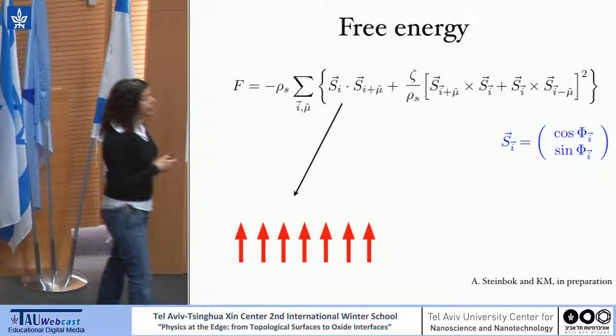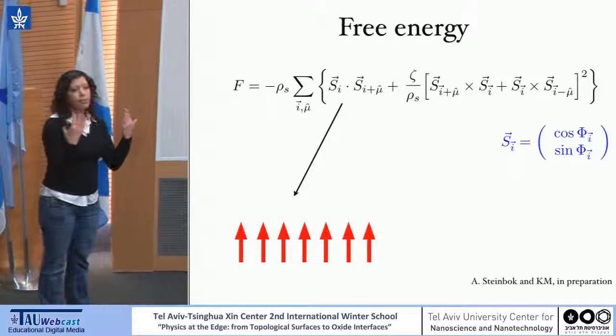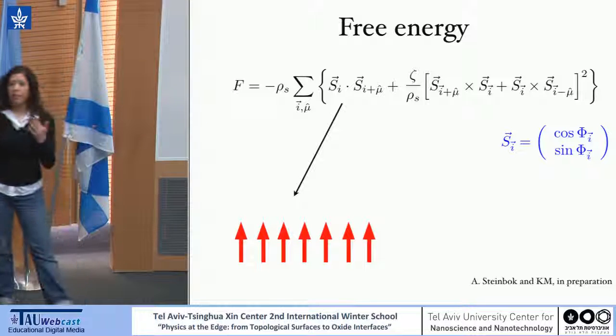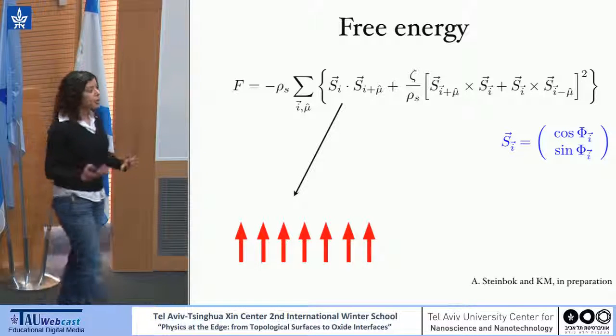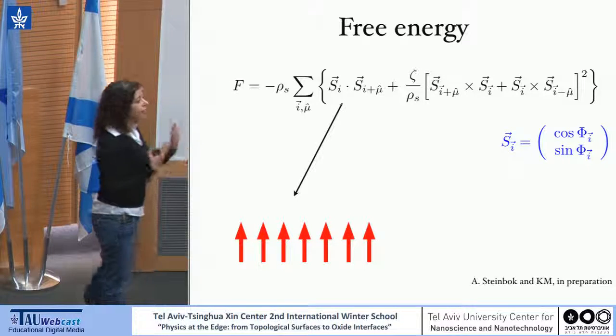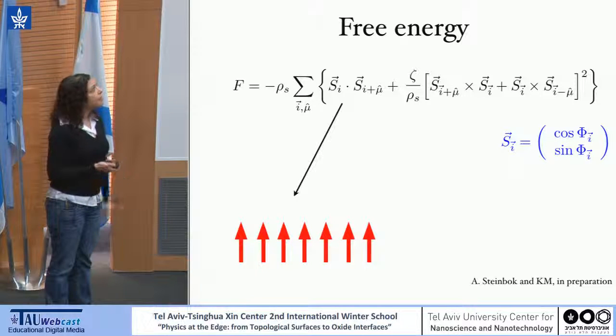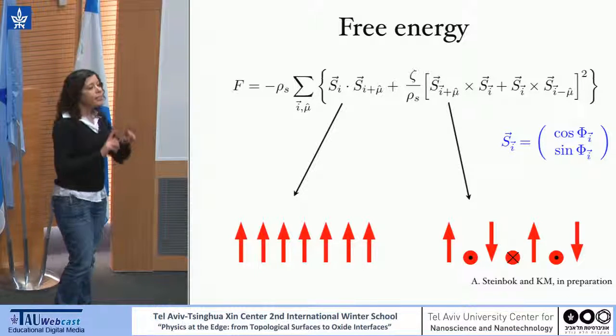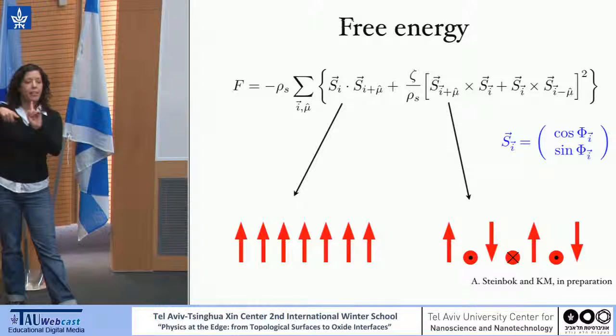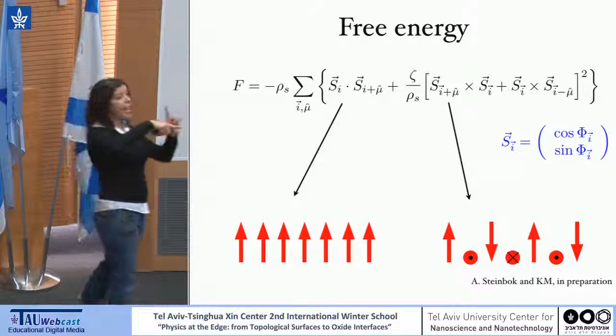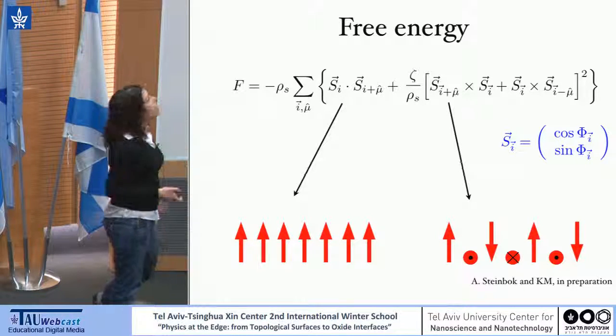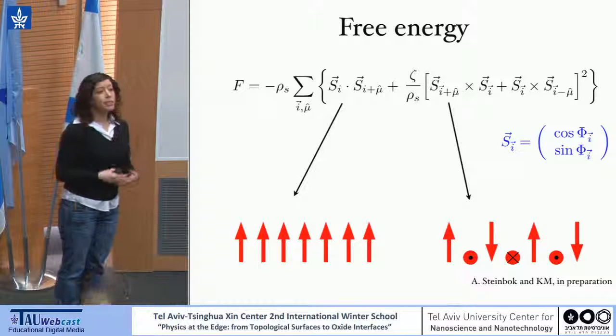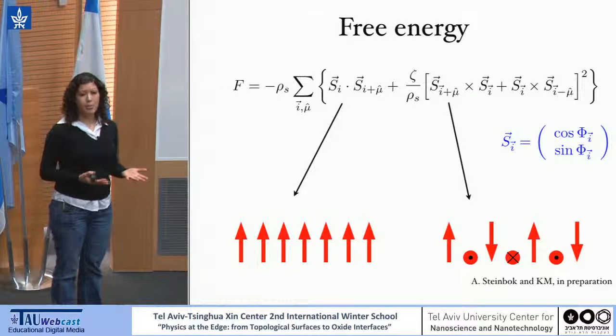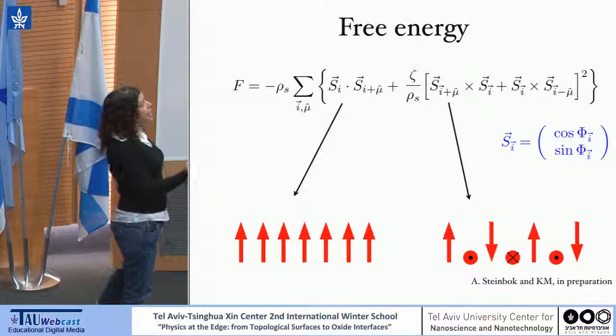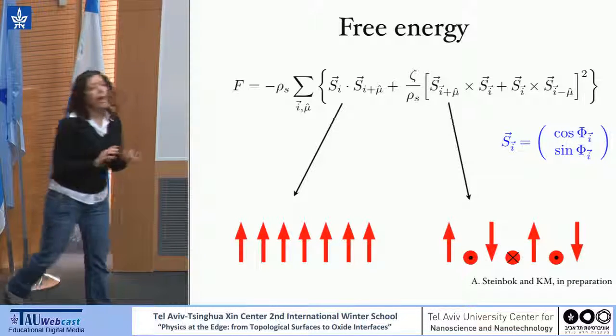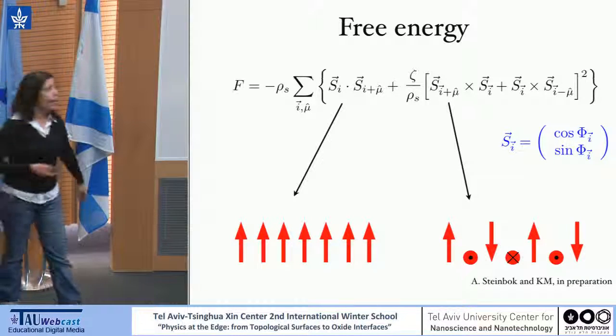So the first term just wants to align all the spins in one direction, or in terms of the superconductor, just to create a uniform phase in the superconducting phase. And the other one wants to actually rotate them at a 90-degree angle between them. So we are getting a model that looks very similar to a frustrated magnet type of model. Basically, we have a ferromagnetic interaction plus some kind of frustrating interaction.